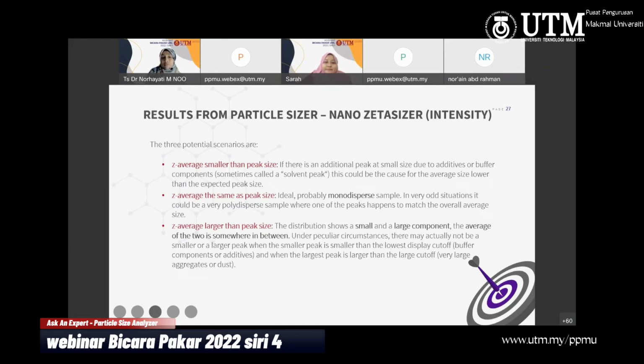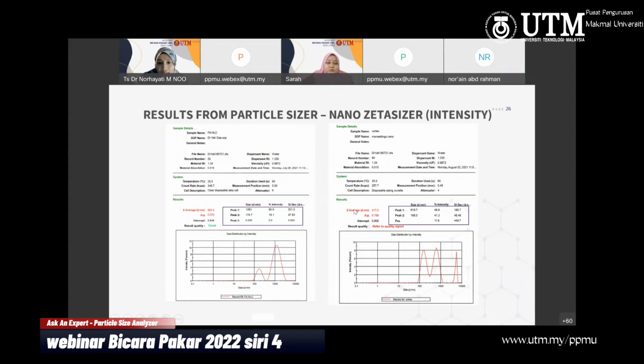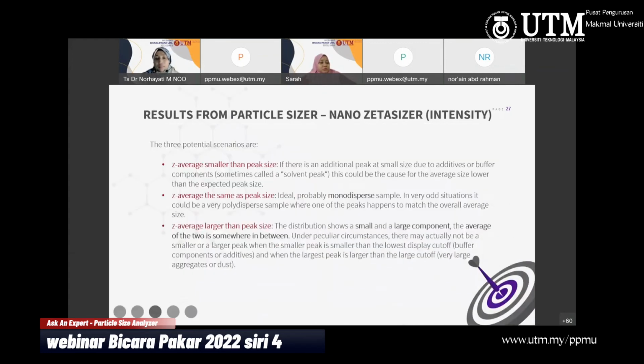All right. If the Z average is the same as the peak size, ideally it is a monodisperse sample. You can see from here, this is the average, and then there is the peak size. They will give you slightly different results, not really large. But if your Z average is larger than the peak size, the distribution shows a small and a large component. The average of the two is somewhere in between. Under peculiar circumstances, there may actually not be a smaller or larger peak when the small peak is smaller than the lowest display cutoff. So it could be some other materials involved in your preparations, right?